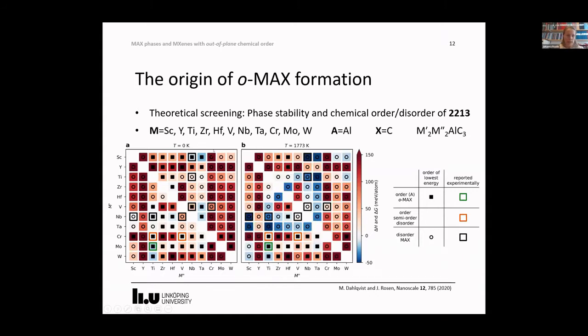But again, if we increase the temperature, we see that many of the ordered phases turn into disordered ones. But we also see suggestions for new interesting OMAX phases based on, let's see, tungsten, titanium, molybdenum, tantalum, and niobium, hafnium. And this means that there are several suggested OMAX phases here that are just waiting to be discovered.